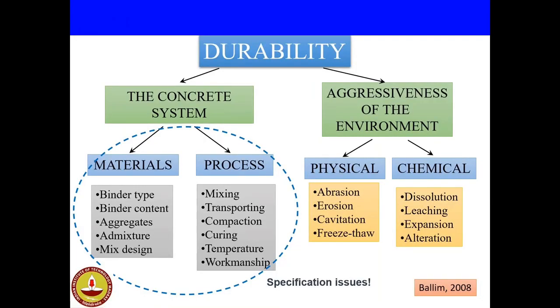When we think about concrete durability, the durability issues can happen either from the concrete system or from the aggressiveness of the environment. The concrete system involves the materials that we have used for the construction, for example, the binder, like PPC or PSC or ordinary Portland cement, or a combination of OPC and any supplementary cementitious materials like slag, fly ash, silica fume, etc. How much is the content? What are the mix design parameters that we have adopted? The type of aggregate, the quantity of aggregate, the admixtures, their quantity. So everything coming under the material section.